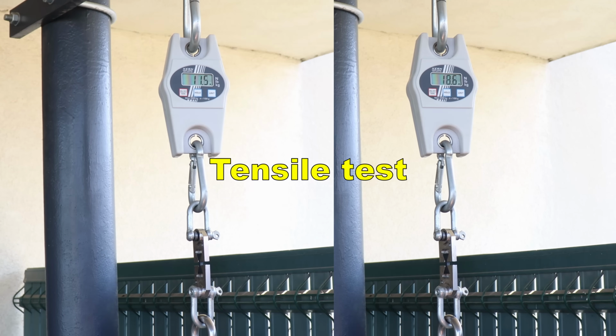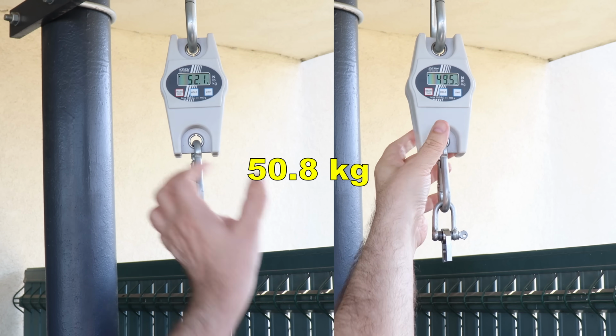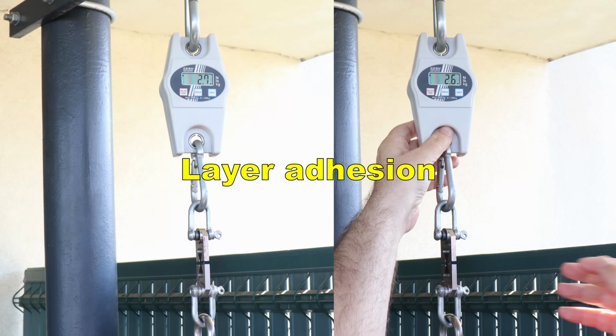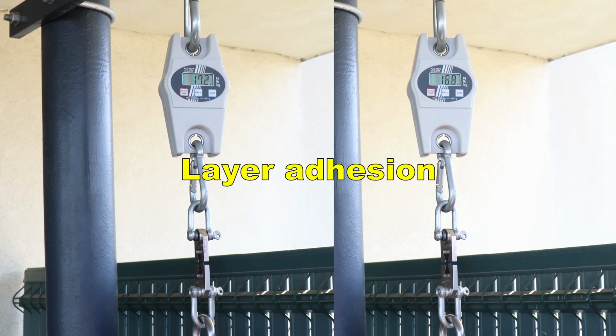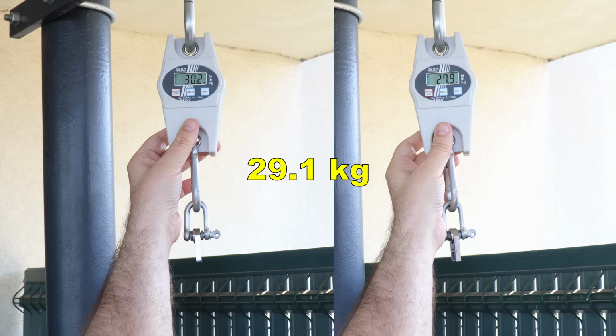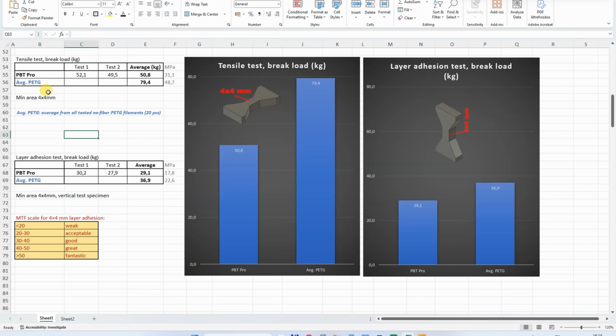It's time to start the mechanical testing. And on screen you can see the average from 2. Layer adhesion. These are solid inside. Since print settings are very similar to PETG, I decided to compare to this material, and I have here 20 pieces in that summary table from my Patreon supporters. And on a tensile test we can see that PBT is noticeably weaker. Layer adhesion is weaker too, but it is somewhere between acceptable and good layer adhesion.